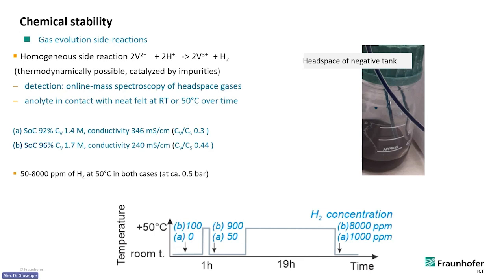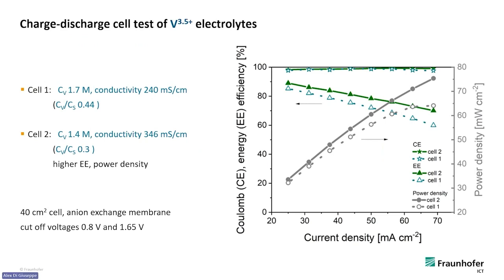Fortunately, the 1.4 electrolyte, which is electrolyte A, so we have a program where you have a 1 hour peak where you heat it up and then cool it down, and then have a 19-hour heating period, and in between we measured, and we could actually show that the 1.4 molar electrolyte has less gassing than if we operate, for example, the 1.7 molar electrolyte. This got us quite thrilled that this was also stable. So we then made a comparison between a 1.7 molar, which is more or less a regular electrolyte, and this diluted electrolyte. And we could also see that we have much higher power densities, and this has to do with the higher conductivity.